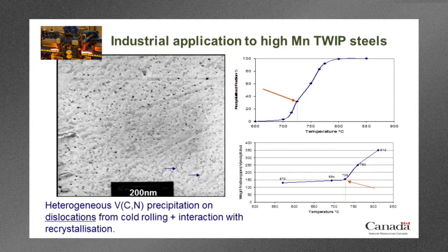And below that, what we have is another curve where we did selective chemical dissolution, and we're looking at the amount of vanadium precipitated as a function of temperature as we were going up in this recrystallization annealing step. And what we found is that the amount of vanadium that's precipitated, this is in weight ppm here, is actually quite low until we hit this temperature here, which is, I think, 725. And there's a sudden increase there.